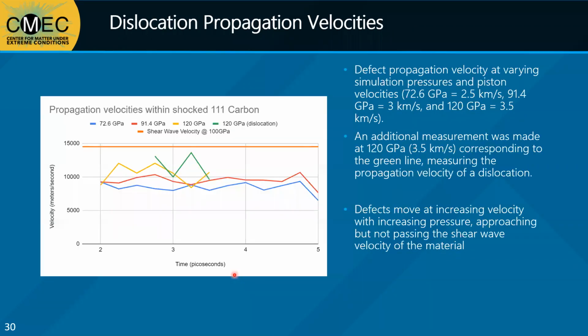We also tracked the propagation velocities of defects in the 111 case. These track the velocities of the stacking faults in the material, with an additional measurement for the half loop dislocation in the 3.5 kilometer per second case. We can see that as the piston velocity rises, so too does the propagation velocity, and we begin to approach the value for the shear wave velocity of diamond.